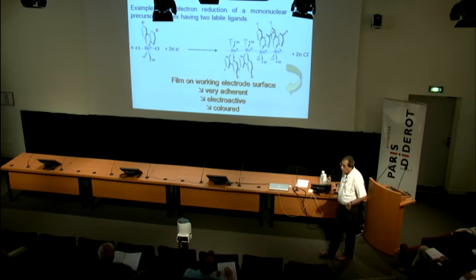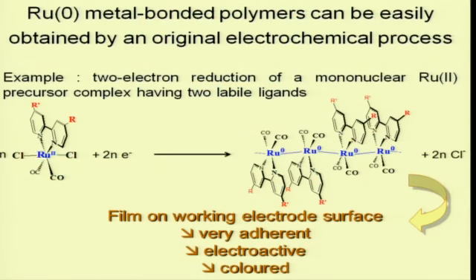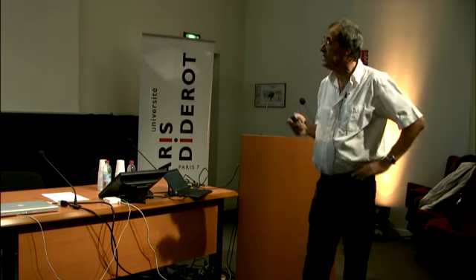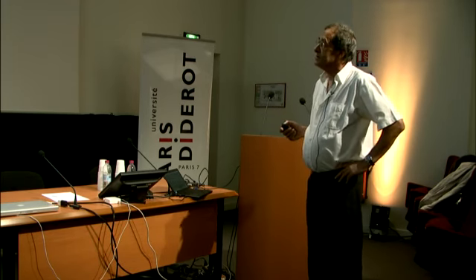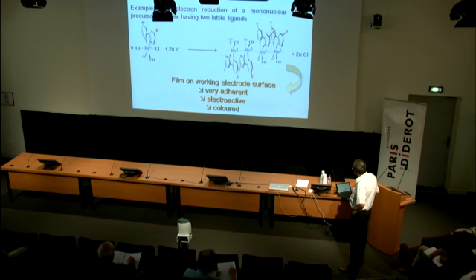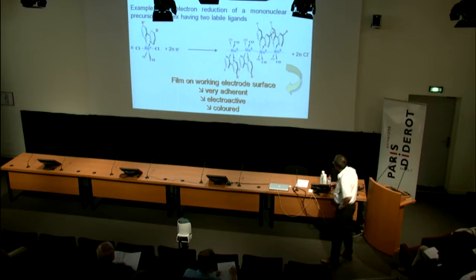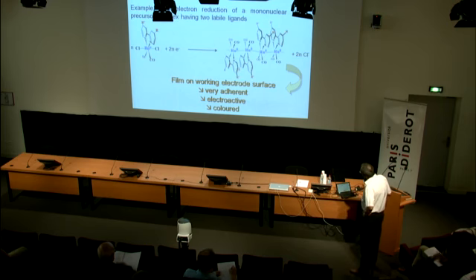So, how did we make that? We made that by electrochemistry, but it's possible to make it also by photochemistry or by chemistry. It's just necessary to use a convenient reducing agent. With electrochemistry, it's possible to make a film of this stuff very easily by a 2-electron reduction from a mononuclear ruthenium complex precursor having 2 labile ligands. And this kind of polymer film is very adherent, electroactive, very important, colored.